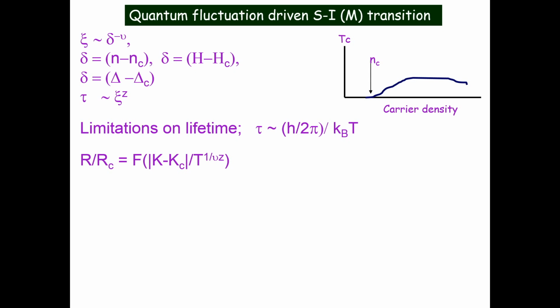So that could be carrier density, that could be magnetic field, that could be pressure, that could be strain, that could be disorder. There are many things. So this delta, if I look at a carrier concentration driven transition, then I can write delta as n minus nc. This is the critical concentration required. Similarly, the critical field, critical disorder. So you will have a quantum critical point here at T equal to 0. If you cross this line, you go superconducting. Here you are normal.